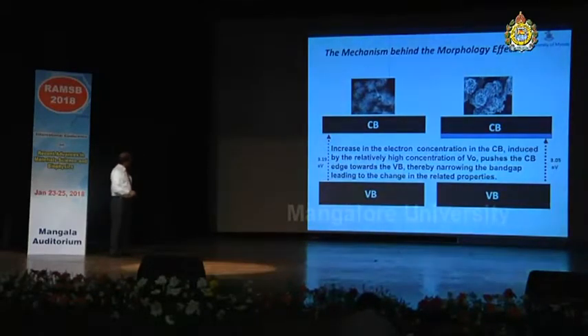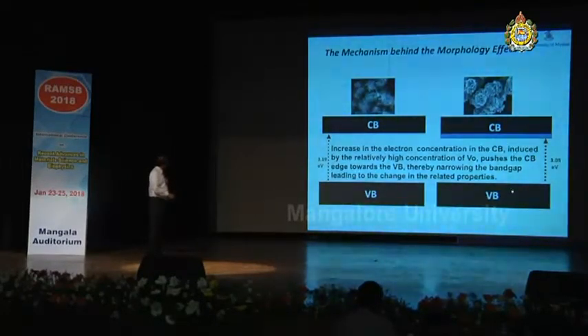And so we can conclude that the increase in the electron concentration in the conduction band, induced by the relatively high concentration of oxygen vacancies, pushes the conduction band edge towards the valence band, thereby narrowing the band gap, leading to the change in the related properties, as you could see here in this wave graph.